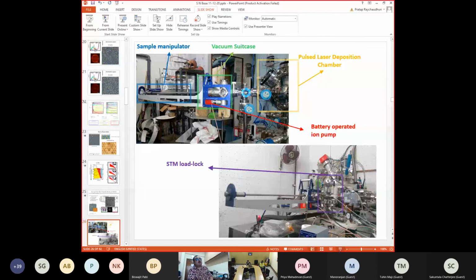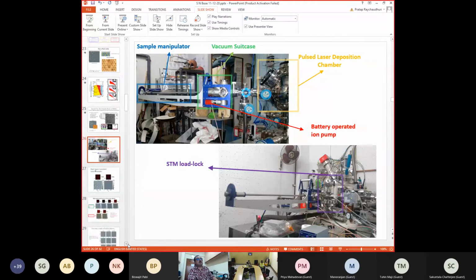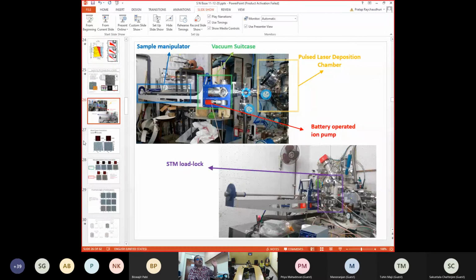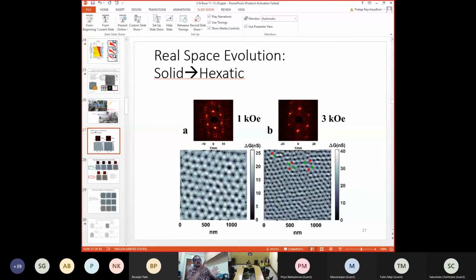Now this is very important, and this is actually the reason why no one had done this measurement on molybdenum germanium, because molybdenum germanium, the moment you expose it to air, it gets oxidized and you don't get any reliable data. Okay, so this is the result.